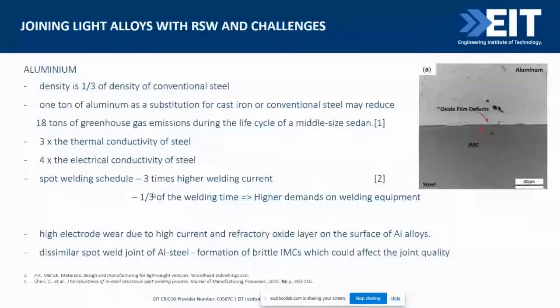Now let's go into the aluminum and magnesium. If you look into the aluminum and magnesium, that is another totally different story. All right. With aluminum as well as magnesium, the important point in here is both of these materials have a very high thermal conductivity compared to steel. Okay. Aluminum is about 3 times in terms of thermal conductivity, 4 times in electrical conductivity, right? And they need a huge amount of current. So aluminum requires about 3 times higher current, happening at a third of the weld time that we use for steel, right?